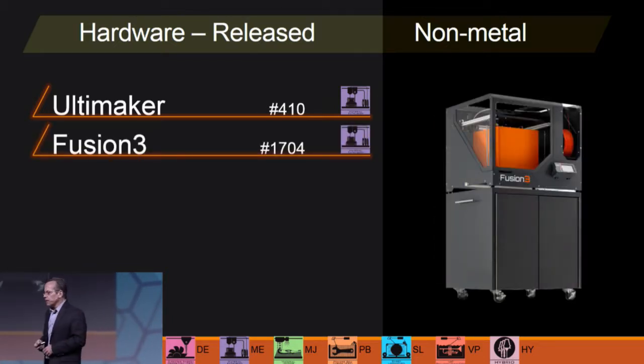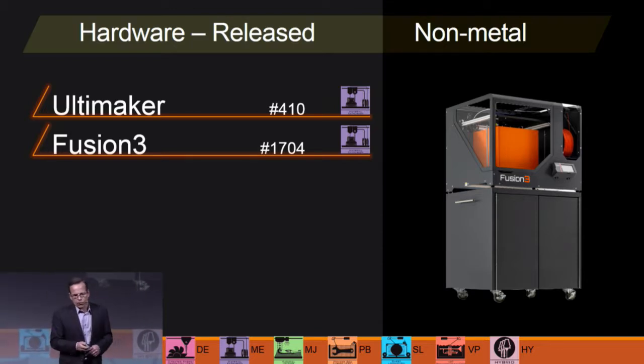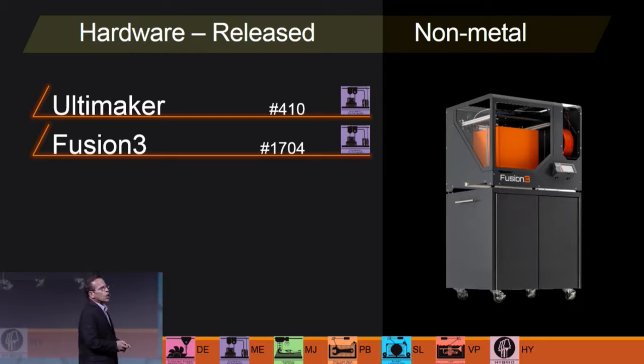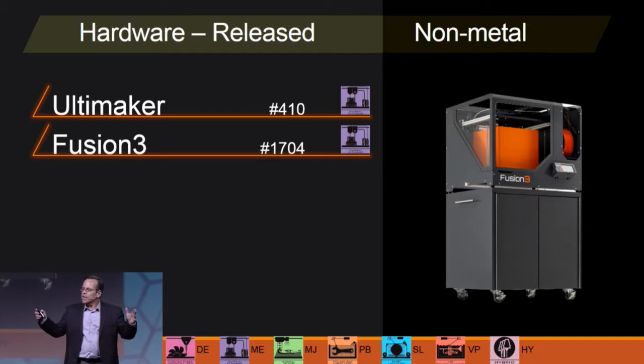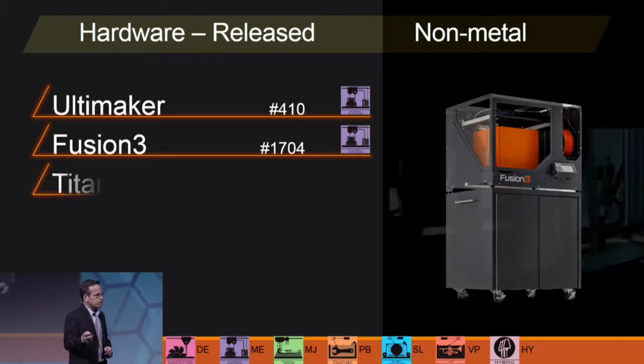Another company tackling the industrial market for material extrusion is Fusion 3. They're here in booth number 1704. Their machine is called the F410. Really reasonable price point, $4,500, running in the 14 by 14 inch build area. And it does have an enclosed chamber. It's not going to maintain high temperatures, but it will maintain temperatures up to 45 degrees C, which helps with managing stresses that can cause deformation in your material extrusion parts.